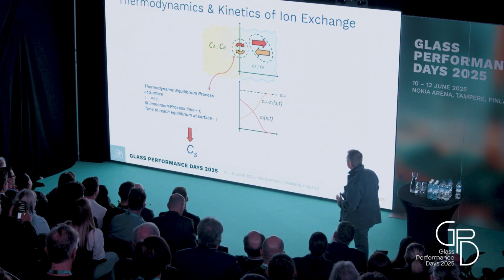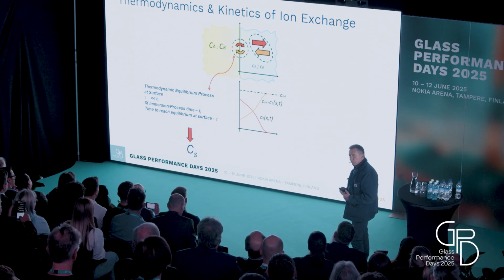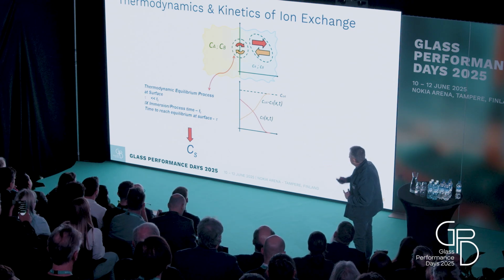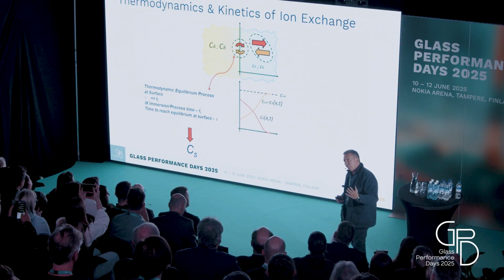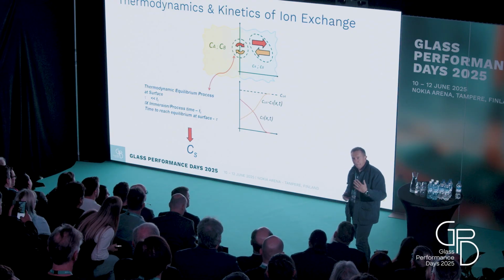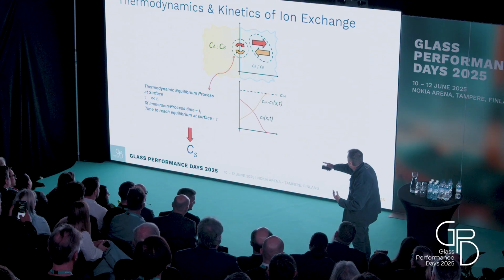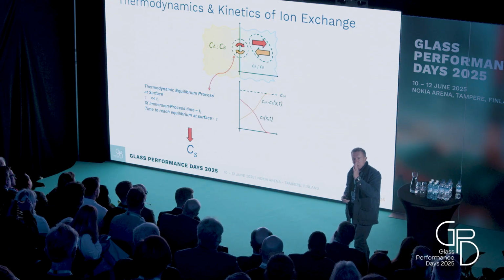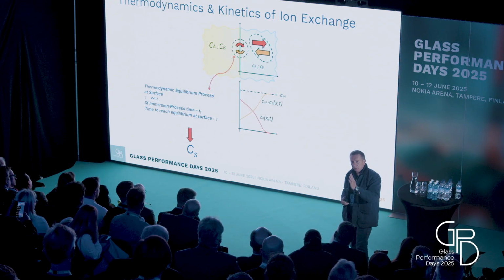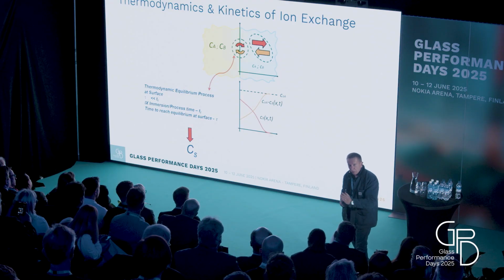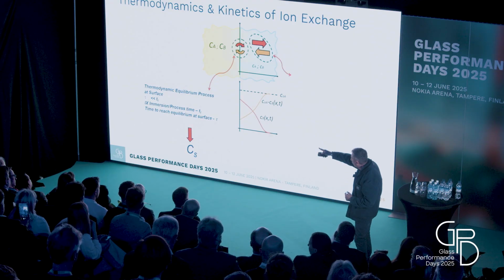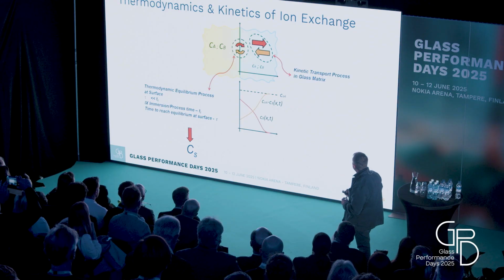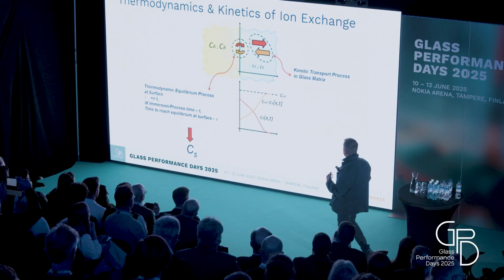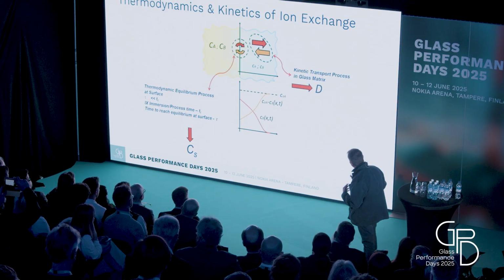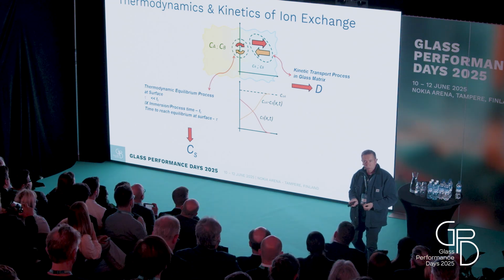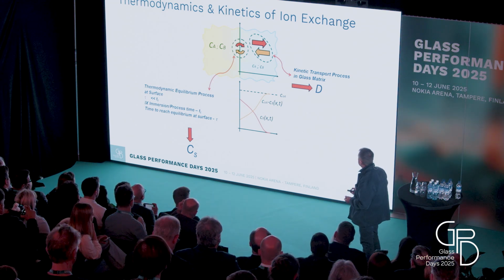This allows you to define an equilibrium surface concentration. This will be important because, for those who normally use mathematical modeling of this process, it gives a boundary condition of constant surface concentration. But again, this is an approximation that is true only under that condition. The other one is the kinetic transport process in the glass matrix, and this is characterized by another parameter, the interdiffusion coefficient, which is a kinetic element.